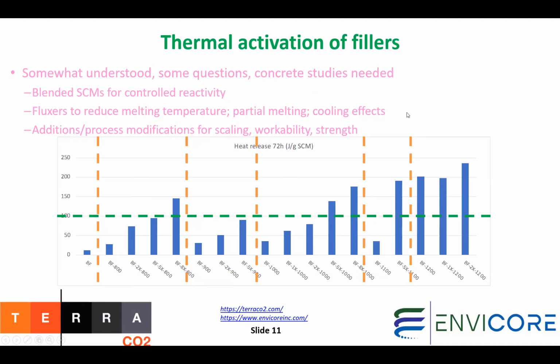So apart from that, there's a couple of other unanswered questions. One is blended SCMs - by blended SCMs, I mean what happens when you start introducing a source of calcium into the glass. Most of what we've melted has largely been aluminosilicates, with very little calcium in there. But calcium has very interesting effects on depolymerization, etc. Calcium increases the reactivity quite substantially.